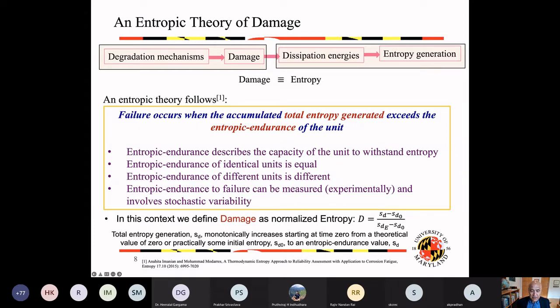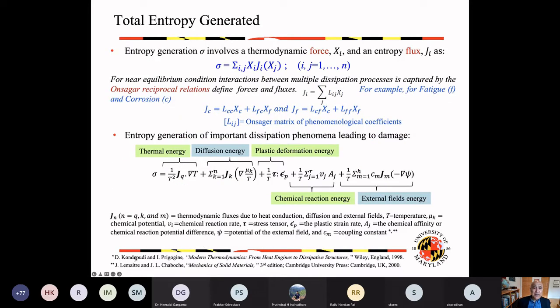So we can also normalize damage by finding the entropy at each point minus entropy at time zero, and dividing by the entropy at the time of failure minus entropy at time zero. So this is entropy at time zero, a brand new component, and this is the entropy currently, divided by the entropy at the time of failure minus the entropy at time zero. So with that, how do we calculate the dissipated energy?